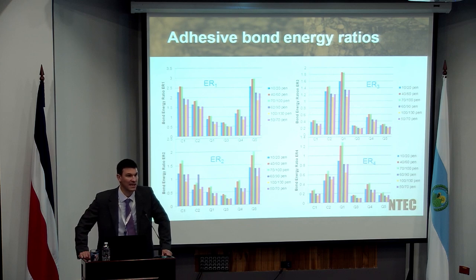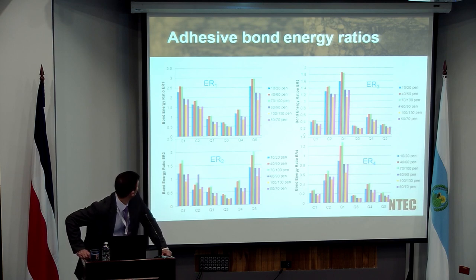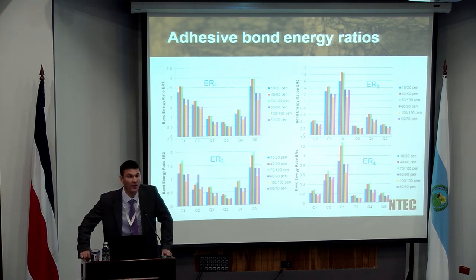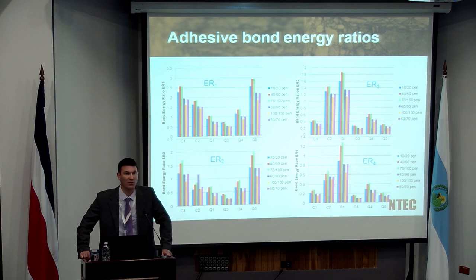So if we look at the top left-hand corner, we can see that straight away there are two combinations of aggregate and bitumen that are giving us extremely low values. I don't know whether the values have come up, but anything less than one in terms of that energy ratio is going to straight away indicate that material combination is going to be highly susceptible to moisture damage.